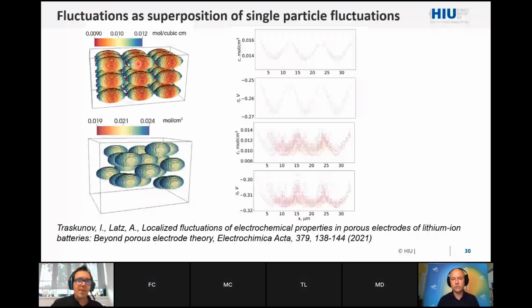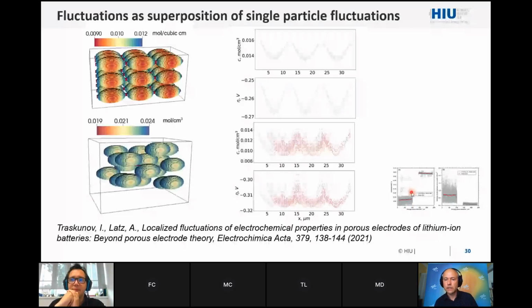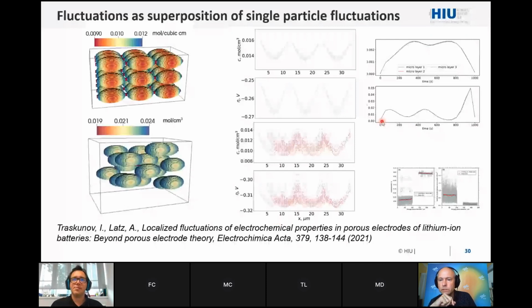But if you then choose an irregular situation, you get basically a superposition of all these particle-origin fluctuations. Of course, we didn't try to recover exactly what we did with Jochen, but you see that if you wouldn't know that this is coming from this regular shape, if you just look here in the middle, you would say, well, okay, this looks extremely random, but it's nothing else but a superposition of single particle fluctuations, which you can exactly predict. And this is what I said before, that depending on the SOC, here we have against time a fluctuation in the overpotential, where the overpotential is double as high as it is here. So the stage where you are will also influence whether you get more likely or less likely degradation phenomena.